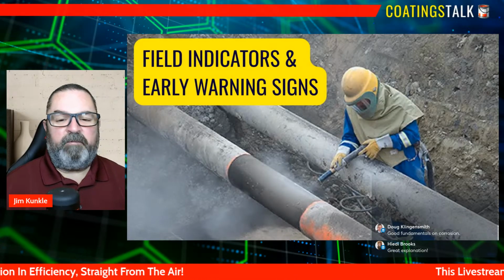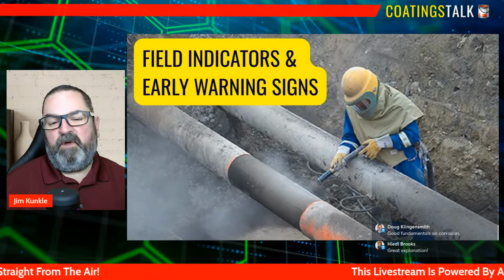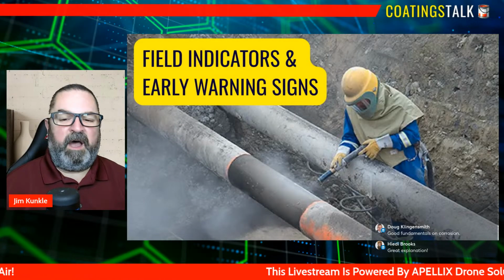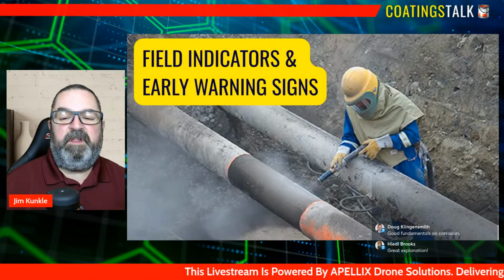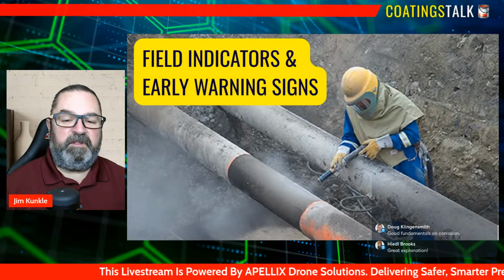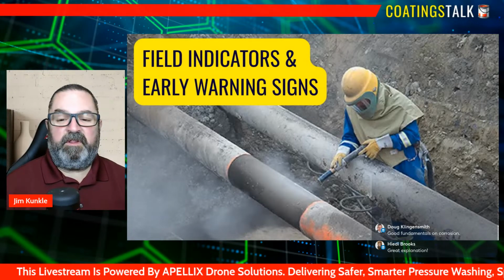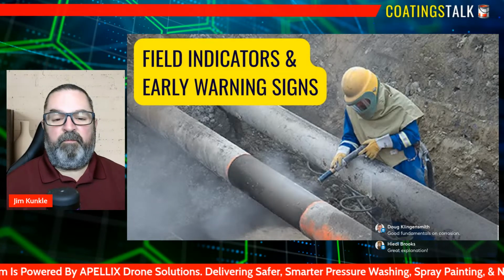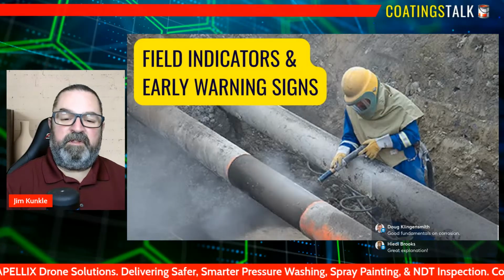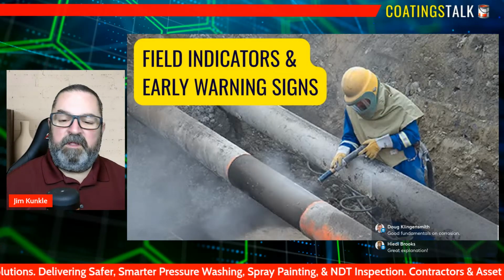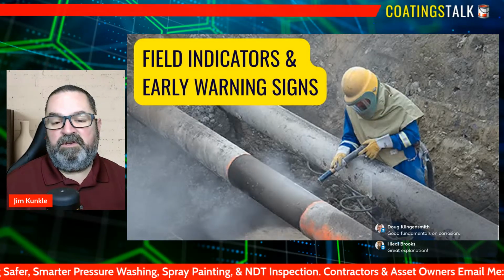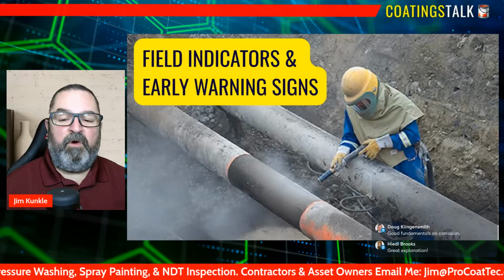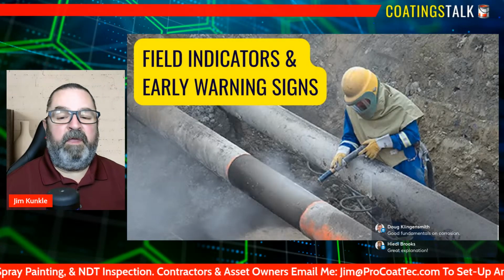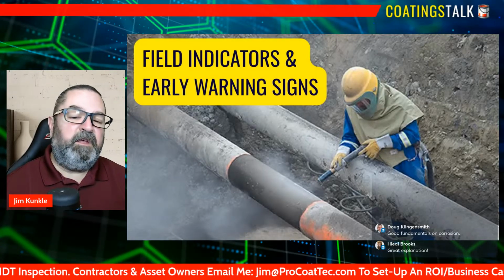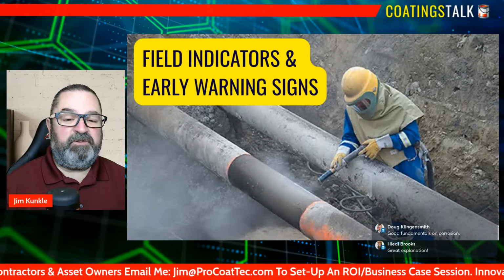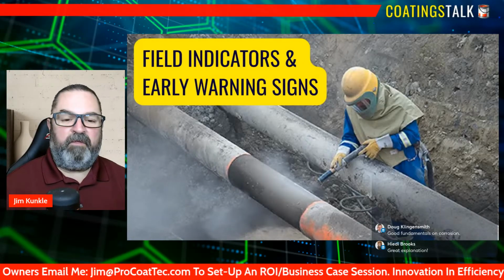Moisture water traps are especially dangerous because they create microenvironments where corrosion thrives. So when you see standing water on horizontal surfaces or condensation under insulation, or when you have debris buildup or tight crevices where moisture can't escape, these all contribute to rapid deterioration. And these areas corrode faster than exposed surfaces because the trapped moisture keeps the electrochemical reaction active around the clock.